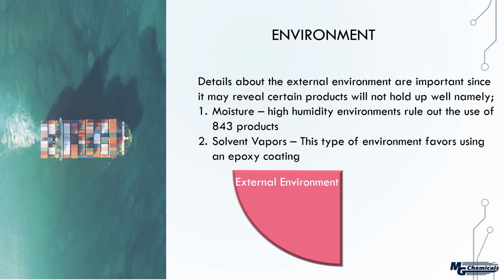So there is a workaround if you want to apply a protective top coat over the 843, but for a lot of people that's more work, more cost, so they're not typically interested. So you'd want to look at another filler system. The other thing is whether the paint is going to be exposed to any kind of solvent vapors. And we talked about this earlier. That does not favor the use of things like an acrylic resin or a water-based system. They simply don't hold up long term. So if that's the case, then really you need to consider an epoxy coating.